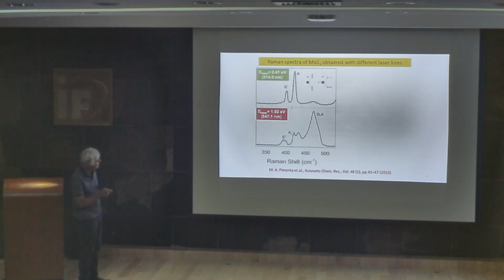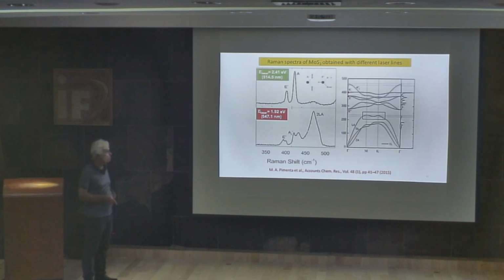But now, for the same sample, I'm just changing the color of the laser. I'm using a red laser, and you can see that now the spectrum is completely different, because in this case the red laser is in resonance with the excitons. Then we have a completely different spectrum, and this band becomes very strong. You can see that the energy of this band is 460 wave numbers.